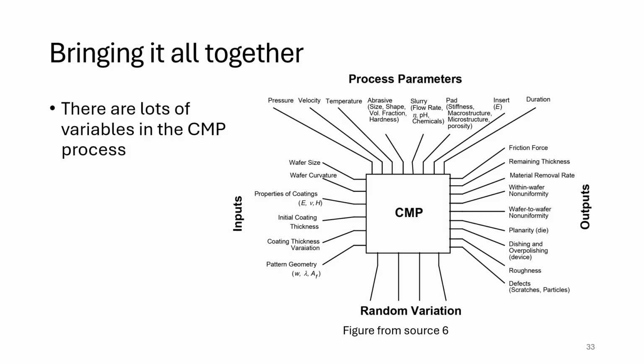Selectivity is important, so that is your target versus stop layer and what you're actually trying to polish away. Uniformity is going to be driven by your carrier head and pressure control, slurry distribution, pad grooves, and feature density on your specific wafer. Pattern effects like dishing in wide metal and erosion in dense areas are managed with design fill, zoning, and correct pad and slurry selection.